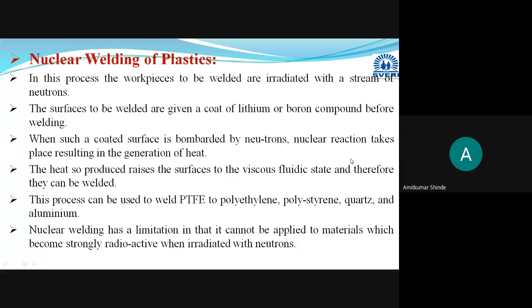A nuclear reaction will occur between the neutrons and the elements present in the coating, lithium or boron, and heat is generated on the surface itself. That surface will start melting, and with the application of some pressure it will get welded, and the desired joint is obtained. In this way, nuclear welding of plastic is performed.